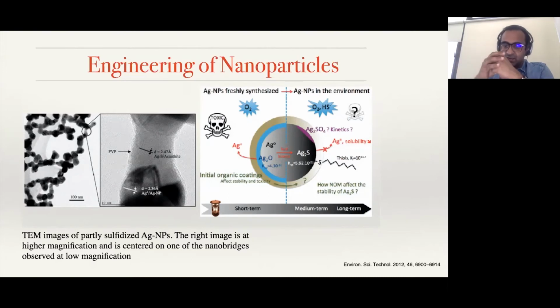So when a cell sees the silver nanoparticle, it does not really see zero-valent silver, Ag0. It actually sees a mixture of various surface chemistries. There can be Ag0, there can be Ag+, there can be AgCl, there can be Ag2S, and effectively, depending upon what my environment is, the same silver nanoparticle can have a very different response. And someone might say, are you really testing the response of silver nanoparticles, or are you actually seeing the response of silver sulfide or silver chloride complexes? That becomes very murky and very tricky. So for example, over here, we see that the TEM images show the silver nanoparticles, and then suddenly there is a bridging happening, and this bridging is happening because of the complexation of silver species which are present there.